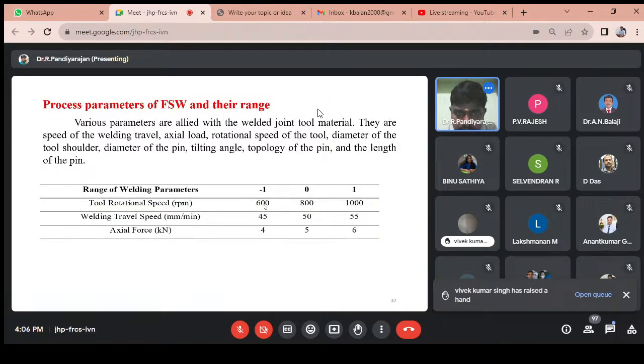For example, we choose 3 levels. The tool rotational speed minimum range is 600; for example, we take 600 rpm as the lower range and the maximum range is 1000 rpm. The welding travel speed minimum is 45 mm per minute and the maximum speed is 55 mm per minute. The axial force minimum is 4 kN and the maximum is 6 kN. There are 3 process parameters and 3 levels.